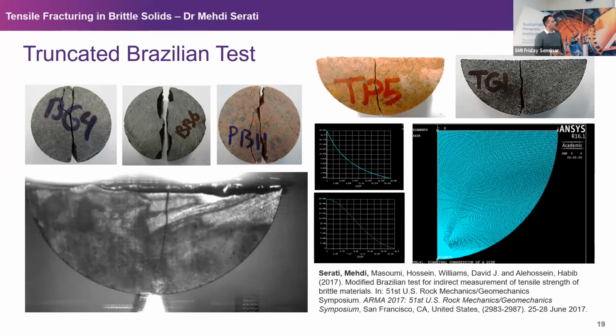So in an attempt with our colleague at UNSW, Hossein Masoumi, you may know him, we proposed that you can cut the Brazilian test sample in half, and by carefully controlling the contact angle at this point, you can get rid of all these unwanted multiple cracking and shear rupture, and you can generate a single beautiful tensile crack. And here you see also the numerical prediction that suggests that the midpoint here experiences the highest induced tensile stress.